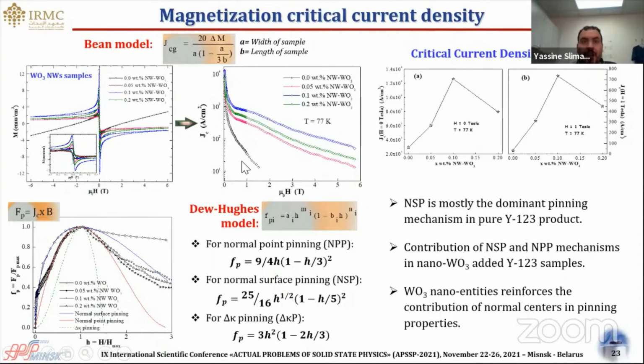Here we found that there is a significant improvement, in the absence and in the presence of an externally applied magnetic field, with the tungsten oxide nanomaterials addition when compared to the pristine compound. The enhancement in Jc value with nanowires inclusion is by a factor of approximately 4 to 5 times in the absence of an applied magnetic field, and by a factor ranging between 20 to 25 under an applied magnetic field of 1 Tesla. So the pinning strength is reinforced and strengthened with tungsten oxide nanowires addition.